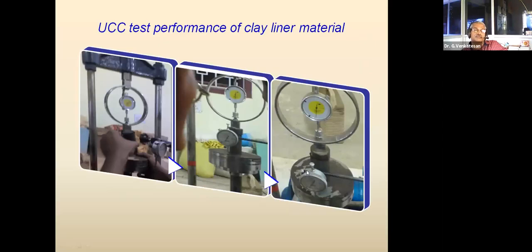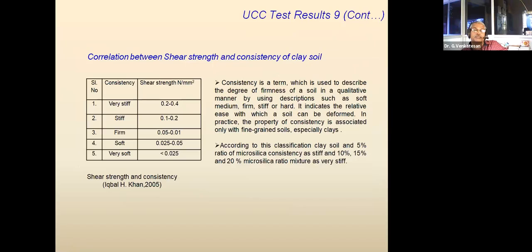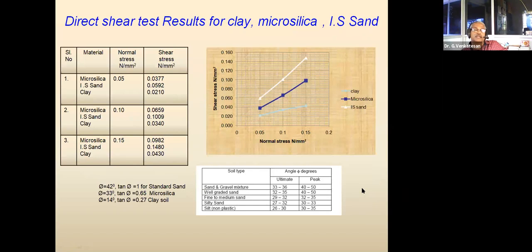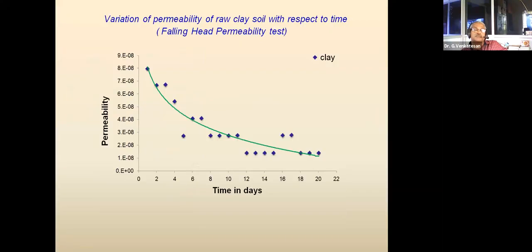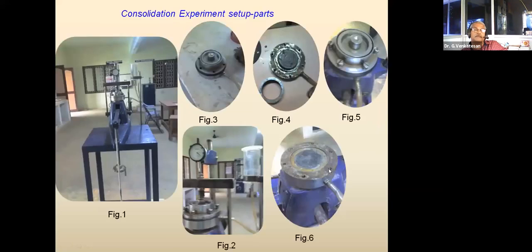This is the test of the clay liner material. Based on the data, we conclude that the soil is classified as very stiff, firm and soft. According to our classification, clay soil with 5% microsilica is consistently stiff, and with 10% and 20% microsilica the clay is very stiff. This is the direct shear test result of clay microsilica as per IS. Apart from it, just compare the actual falling head permeability for the clay, whether we are conducting it over 20 days, and how the permeability will vary. This is the consolidation experiment setup.